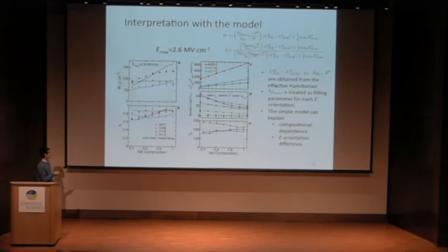Now we can use this model to understand the results. For each composition and each E field direction, all the parameters except this delta E down can be obtained by effective Hamiltonian, as shown in these three figures. And delta E down can be obtained by least-squares fitting to the energy densities and the efficiencies for each E field.